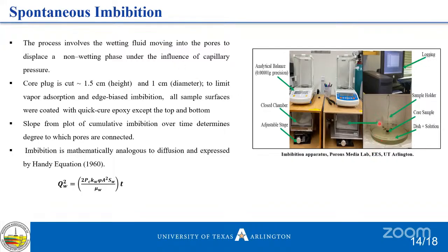So what we did can be replicated in Nigeria because we can always get an analytical balance. I had my undergraduate at University of Port Harcourt, Nigeria. So we can always get this. This can always be bought. And then what we now did was to hang something we can use to hold the core that we have already prepared by cutting it into 1.5 centimeter height and 1 centimeter diameter. You can choose any size depending on what you want to monitor. To limit the water absorption and edge-based imbibition, because we want the water to just flow vertically, we had to coat the sides with quick cure epoxy, except the top and bottom.